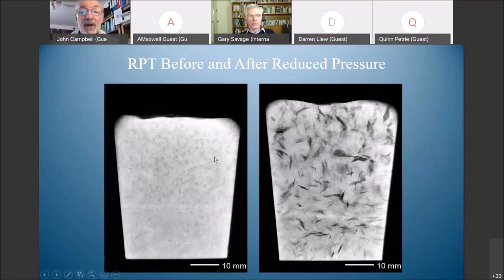But the defect can open up, and here is the same liquid poured at the same temperature with the bifilms now opened by simply reducing the pressure in this case. But there are lots of different mechanisms for opening bifilms. And what you can see is they're huge cracks and they fill the liquid. I mean, this is a useless bit of metal because its properties are going to be so bad. So these are the same metal poured at the same time, the same temperature. This has compact bifilms that have raveled. This has unfurled, opened bifilms, which are really dangerous in terms of properties.